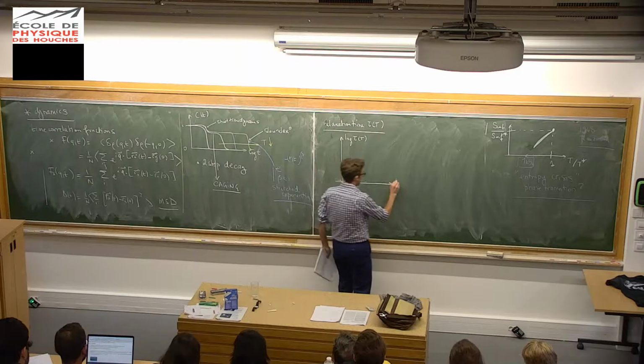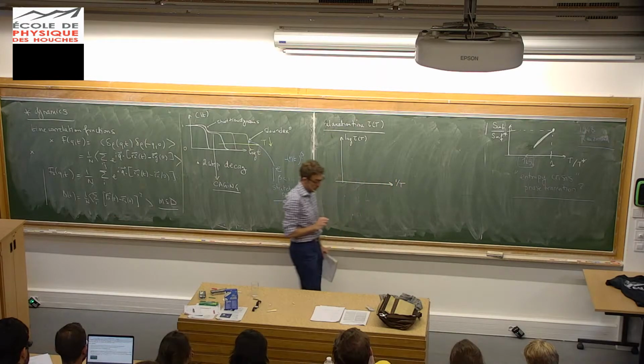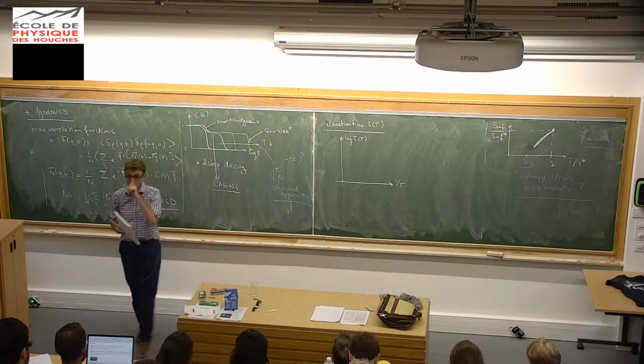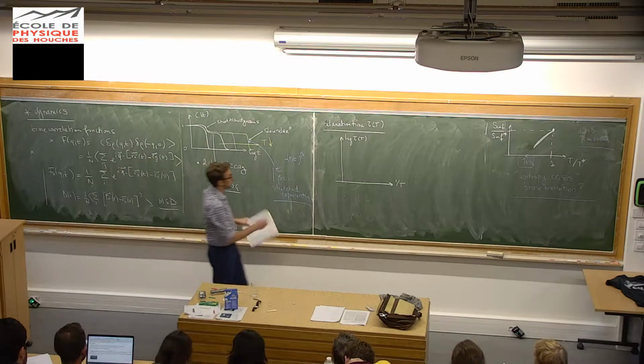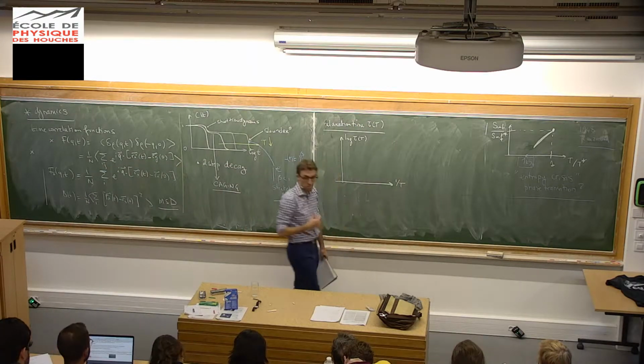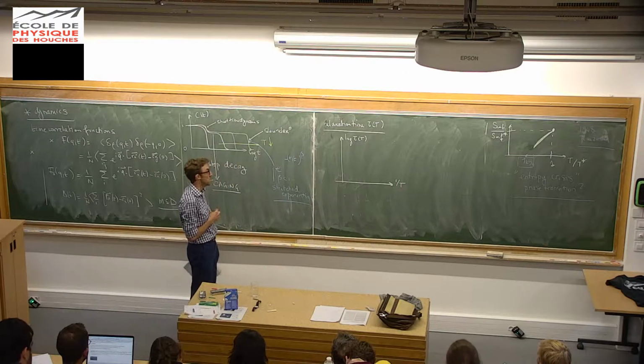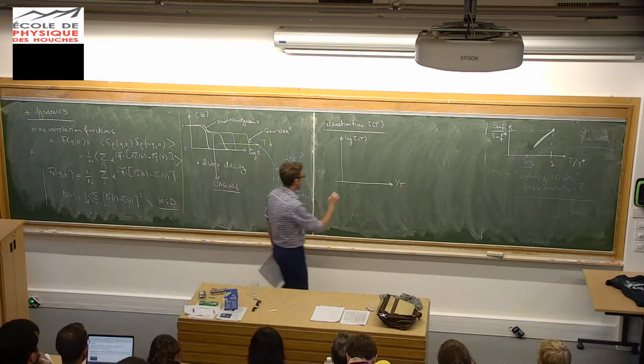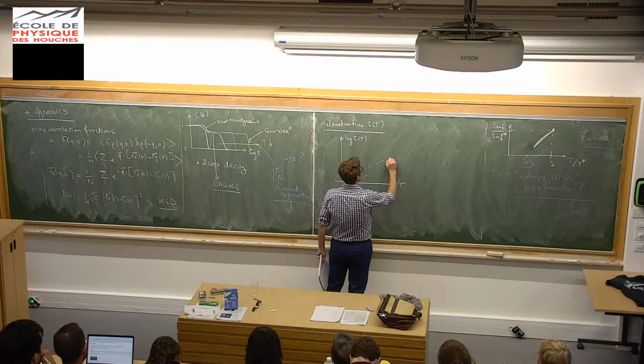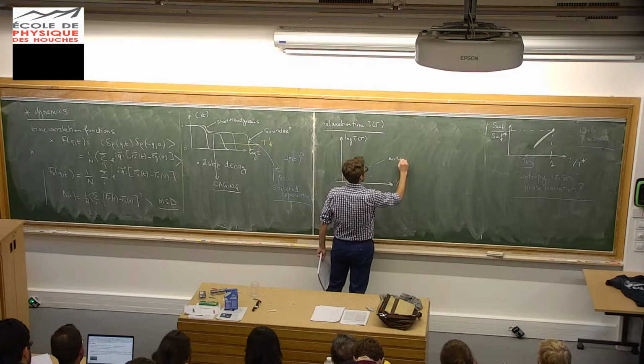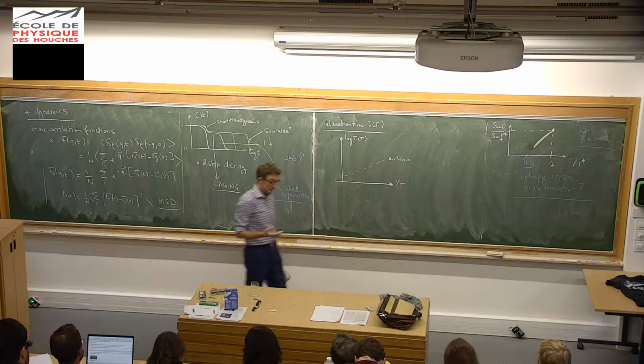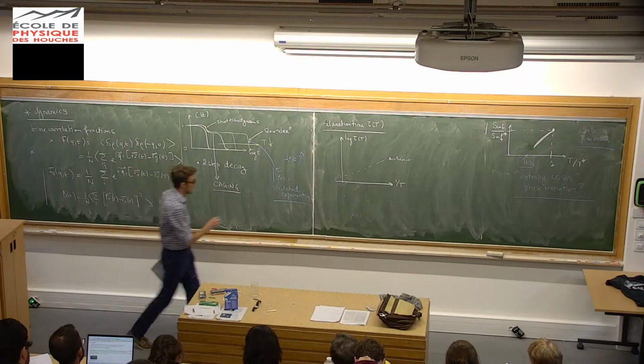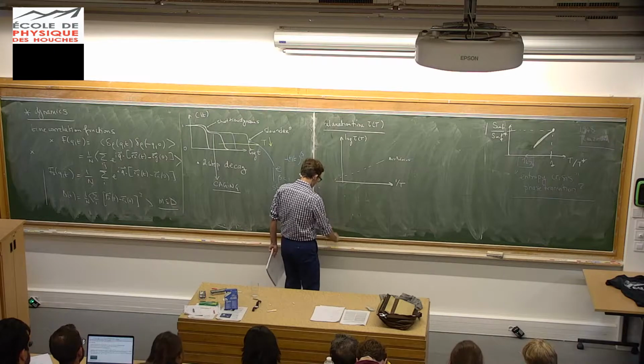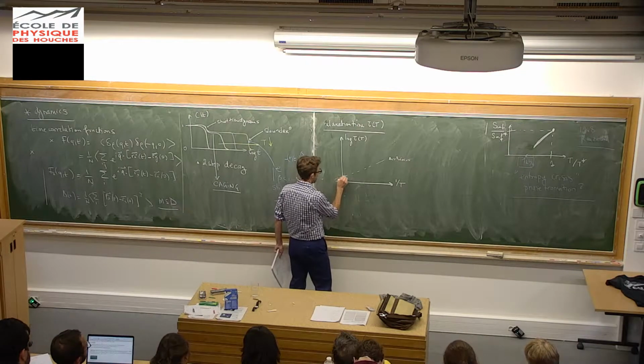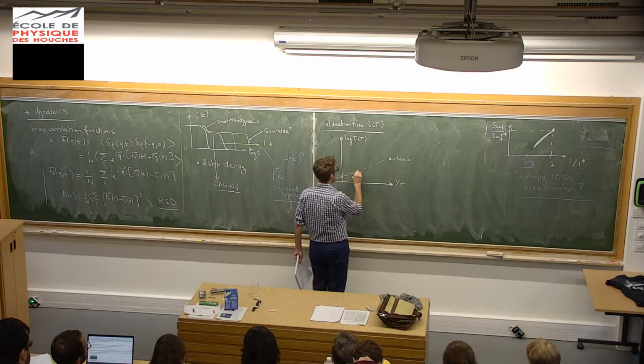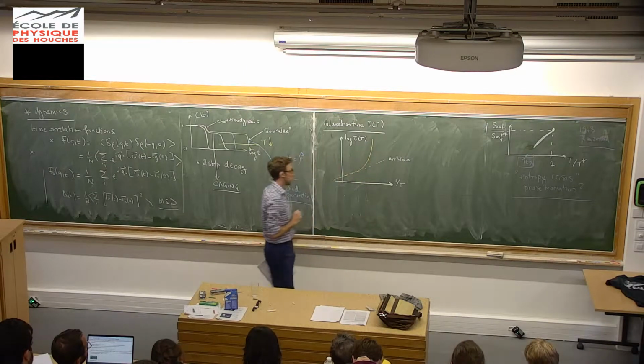And then people show it as a function of the inverse of the temperature. And the reason is that if you have an Arrhenius dependence of the relaxation time, you'll get a straight line here. Okay, so log tau would be proportional to 1 over T, that would be Arrhenius. So anything non-Arrhenius will show in this plot. So that would be Arrhenius activated dynamics over a single energy barrier, and the measurements do follow this Arrhenius behavior up to a point, and then they explode dramatically.